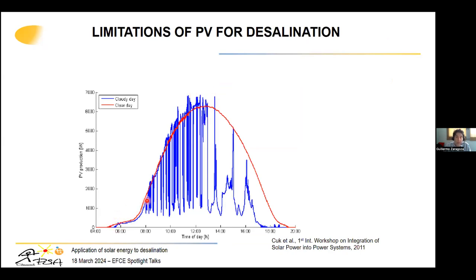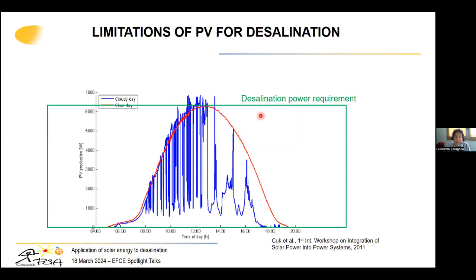You can see that here, this is the production of PV on a clear day, the red curve. Of course, the blue one is on a cloudy day with a lot of variation, but let's choose a perfect day. This is what we can produce. So of course, it's never stationary. And when we want to feed a desalination process with a constant power, we see that if we install the peak power suited to the desalination process, you only have the peak power at midday, the very top of this curve. And the rest is here.